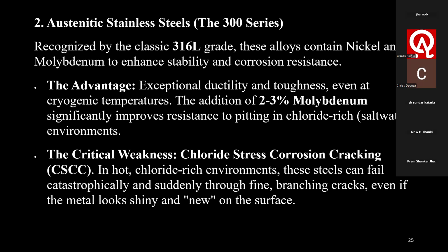But what is the critical weakness? Chloride stress corrosion cracking. In hot, chloride-rich environments, these steels can fail catastrophically and suddenly through fine branching cracks, even if the metal looks shiny and new on the surface.